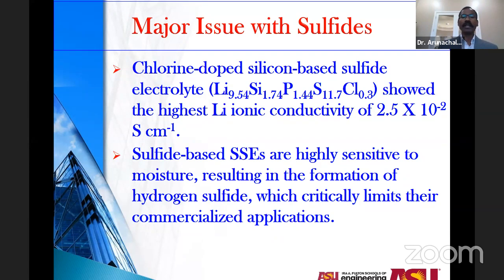That's relatively higher. But these sulfide materials are very, very sensitive to moisture. When the material gets into contact with moisture, it can convert the surface into hydrogen sulfide, and that is probably the major impact which limits their commercial application as of now. But this doesn't mean that the sulfide materials are not going to see the end of the tunnel, but this is one of the major issues right now.